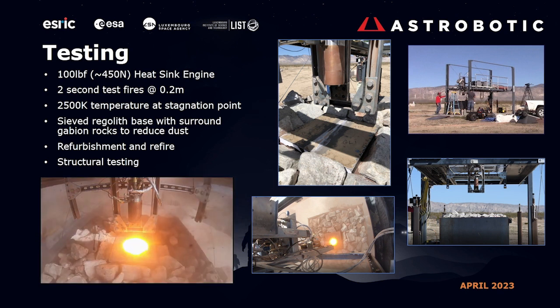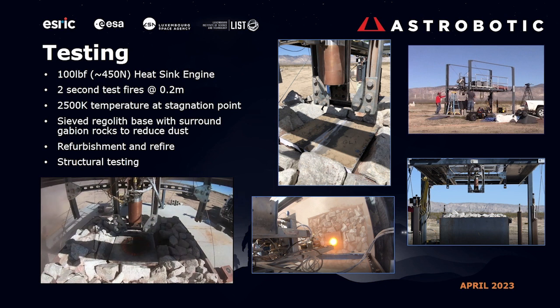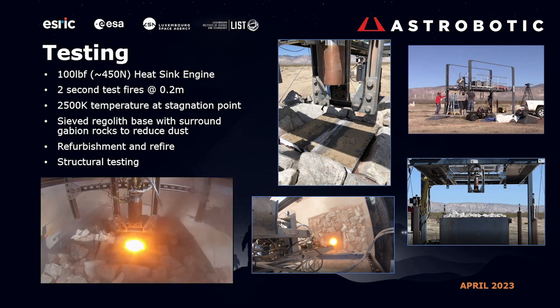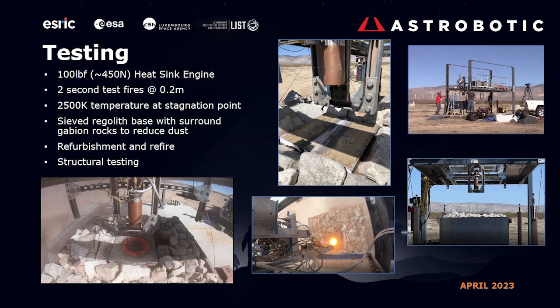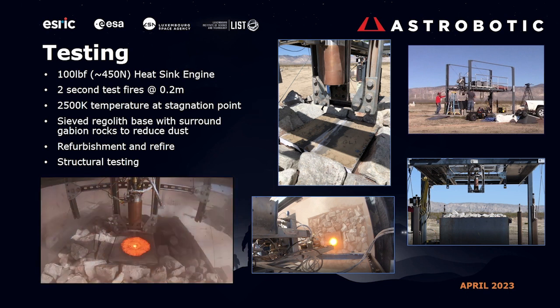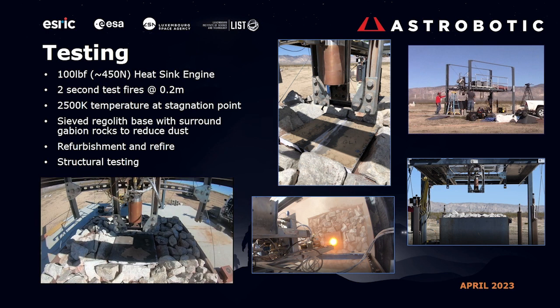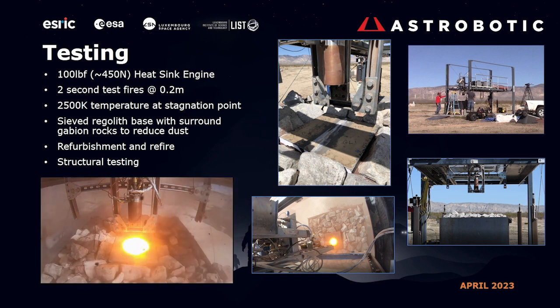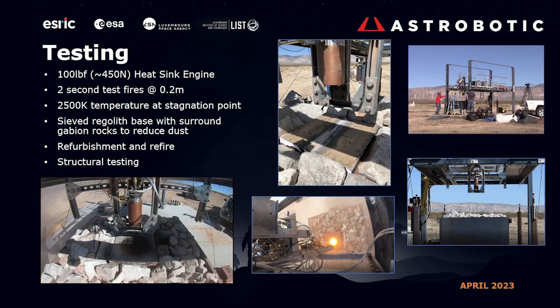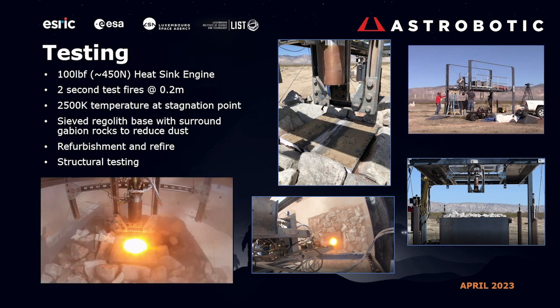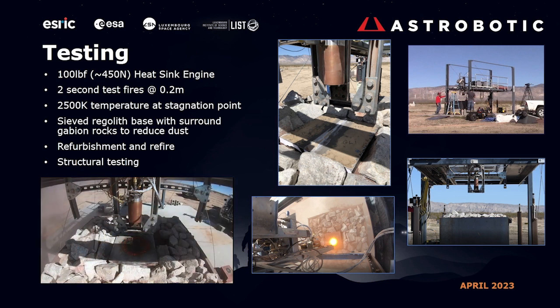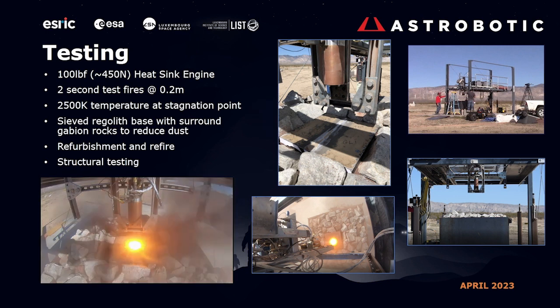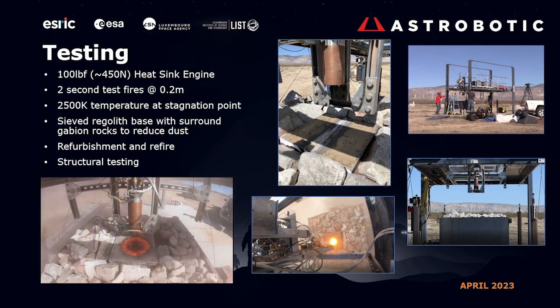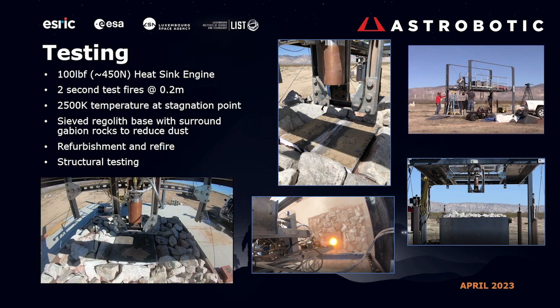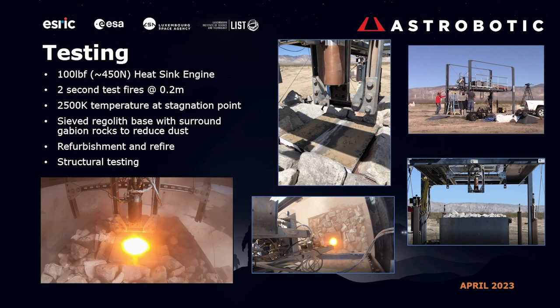And an interesting side note about this setup is that this is the exact setup, both the same engine and the same distance from the ground, that we've proven in other testing causes what we call deep cratering underneath the vehicle. So simulating what it's like if you were to land without a pad, in this exact configuration, we dig a 0.5 meter depth hole underneath the landing site, which is obviously not what you want, but it's an interesting attribute we take advantage of in some other cases for mining and excavation purposes.